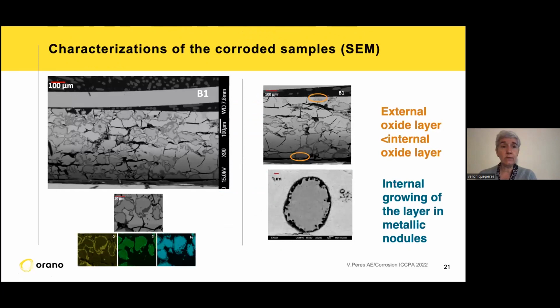If we look at the sample after corrosion, you can see here a very interesting picture. You can see that all the zirconia, which is in this light gray, is cracked, and the cracks are coming from each particle of stainless steel, in more gray here. Around each of these stainless steel particles, you have a dark gray color, which is corrosion, oxidation of the stainless steel particles. And if you see the external layer of the composite here, and mainly near the interface of the stainless steel, there is no big corrosion of these systems.